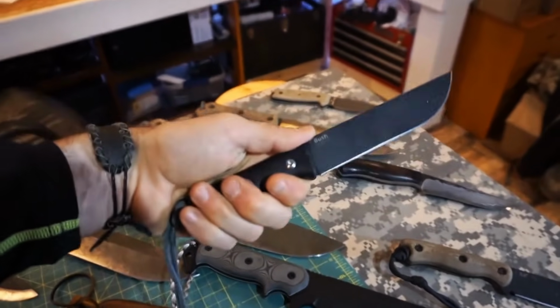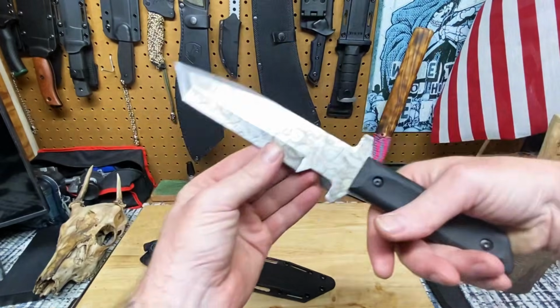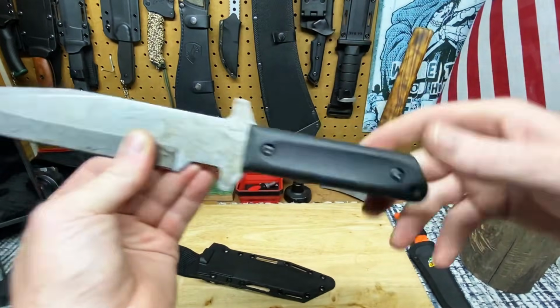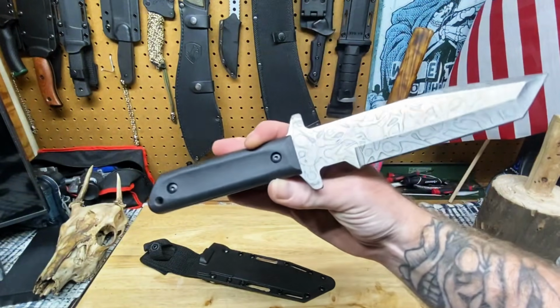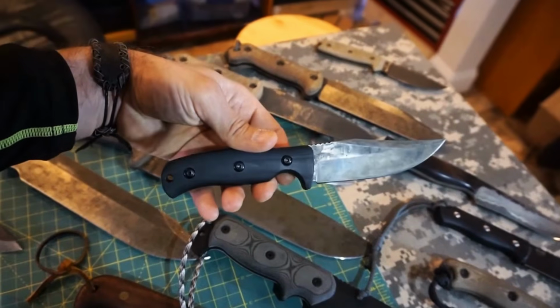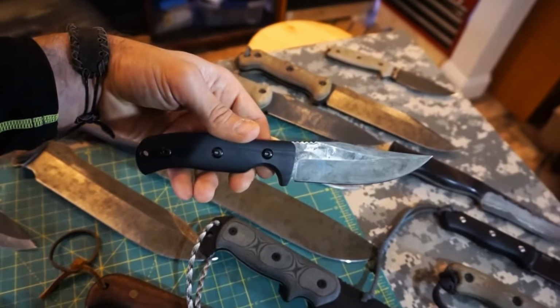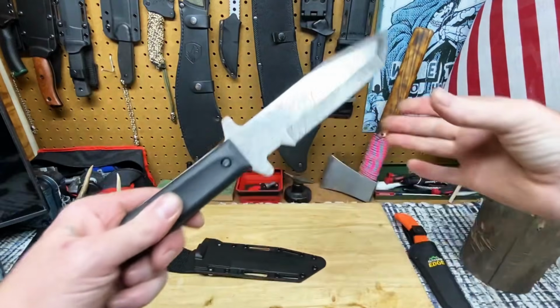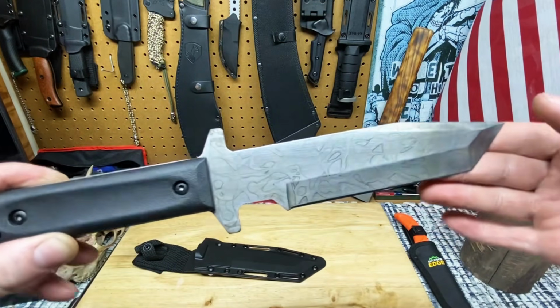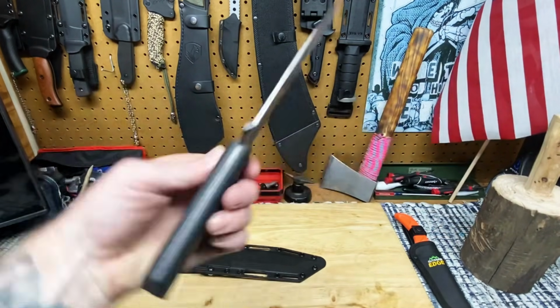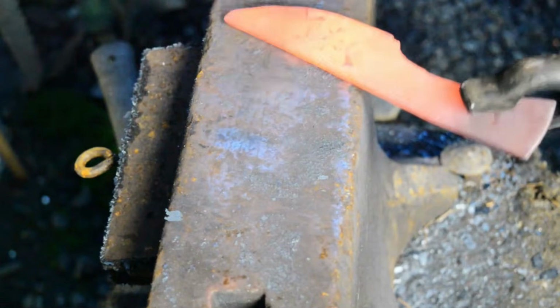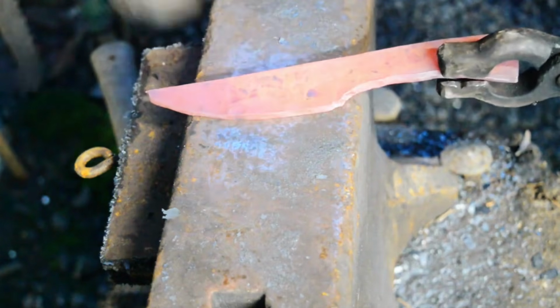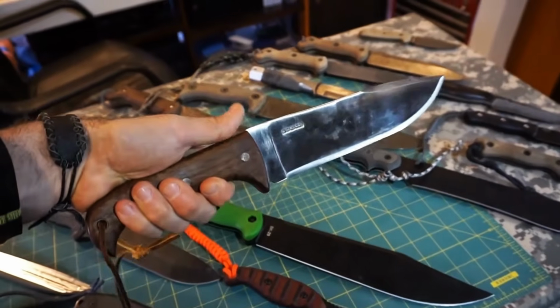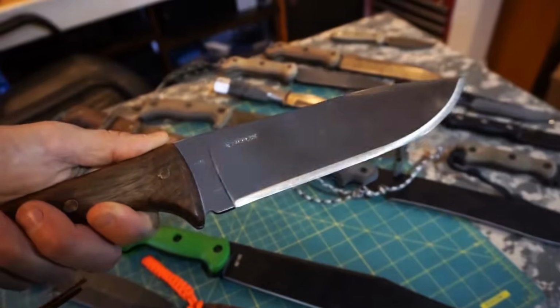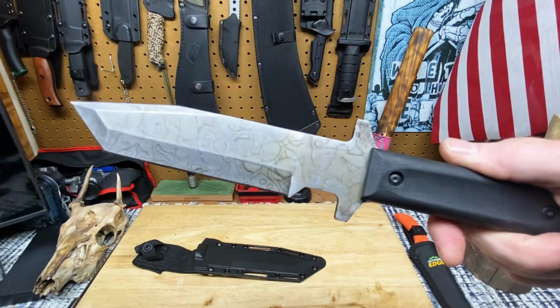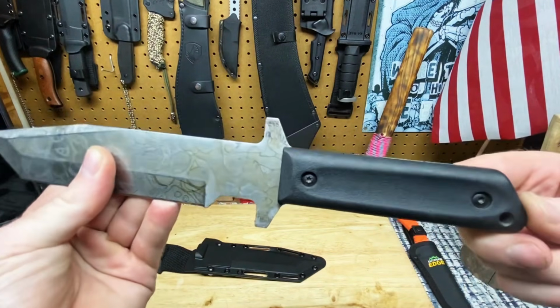Toughness is where 1095 genuinely separates itself from the other 2 steels on this list. In my batoning test, 45 minutes of sustained hardwood batoning, including knotted sections and frozen grain, the 1095 blade came through with a rolled edge and 0 chipping. The D2 blade showed micro chipping at the edge on the hardest grain strikes. The S35VN blade performed better than D2, but still showed more edge damage than 1095 in the most abusive sections.